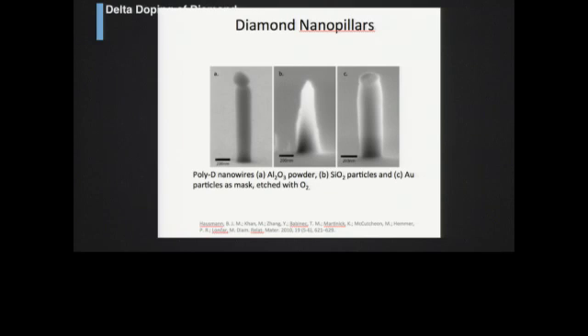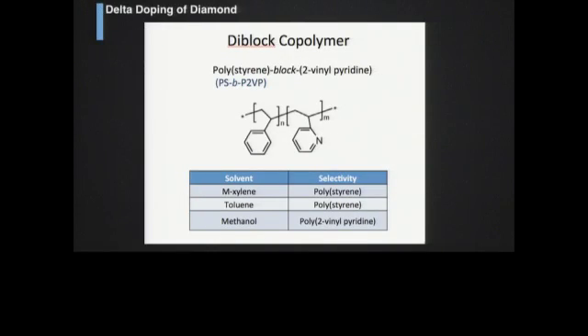We've also been exploring ways in which we could make pillars. Marco has developed a great way using reactive ion etching and e-beam lithography. We wanted to see if we can make some of these pillars using diblock copolymers. So we have a recipe for these diblock copolymers, and the size of the diblock copolymers depends on the molecular weight of these materials.